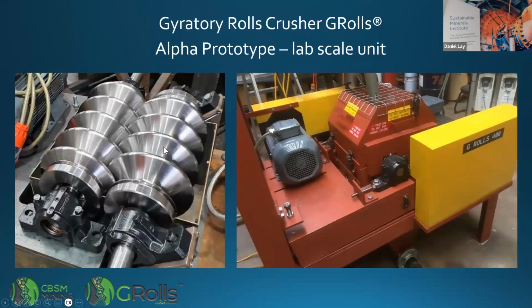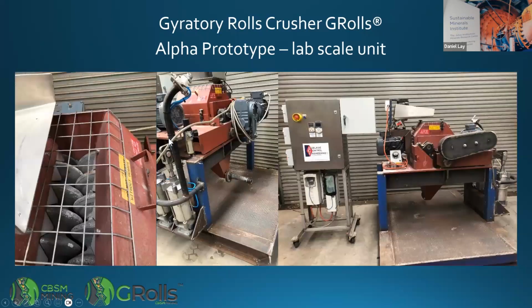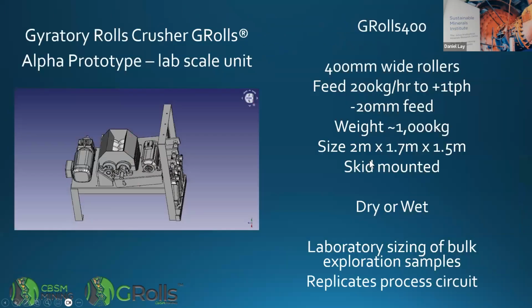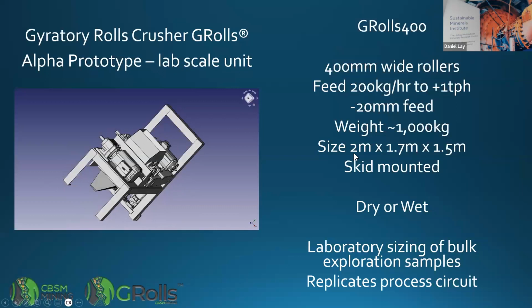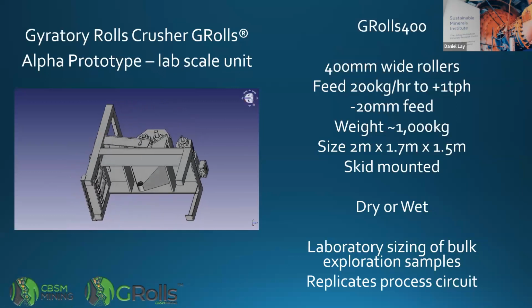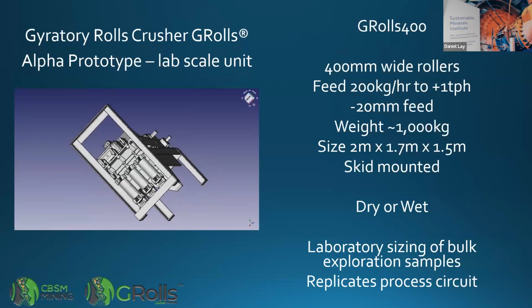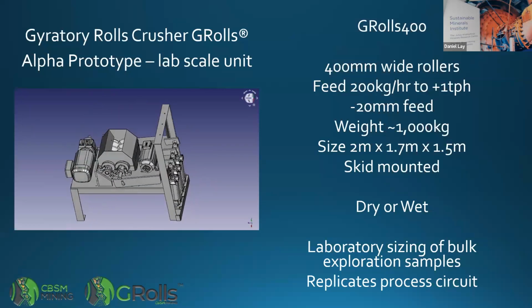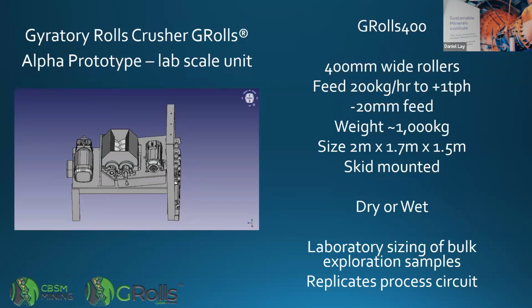So these are the rolls when they're brand new. This is a lab scale unit that we have built to test the concept. It's an alpha prototype. We built the rolls without hardened faces, so that we can see what the wear is like over time. And this is the unit. It's skid mounted, with a control unit. It's a little lab scale unit. The rollers are 400 wide. We can feed materials anywhere from 200 kilos an hour up to 1 ton an hour. It will take up to 20 mil feed. It bounces around a bit, but it still does it.